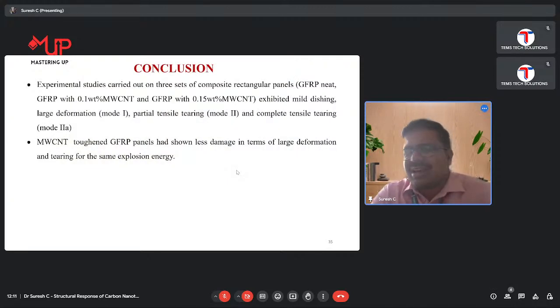From all these studies, we concluded that when we add the CNT, the strength of the composite increases. We have gone particularly for 0.1 to 0.15 percentage of the CNT based upon our literature studies for other things, not for underwater explosives. For other structural applications, the literature says the strength of the composite increases when the CNT percentage is between 0.1 and 0.15, and if you go beyond this, the strength decreases. So we thought to maintain between these two ranges only.